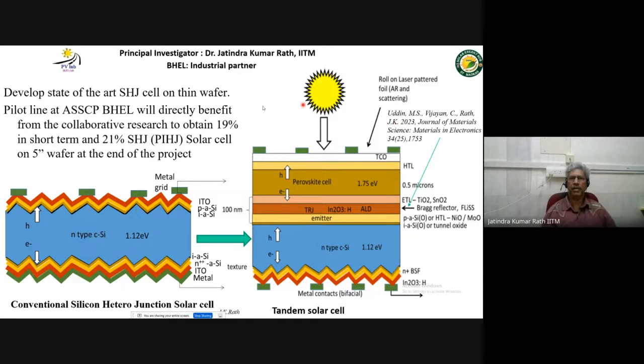So at IIT we have a PhD project to make what is called a heterojunction solar cell. The heterojunction solar cell means crystalline silicon with thin film amorphous silicon as passivating contacts and emitters. So in the PN junction, the P layer is amorphous, whereas the N layer, this absorber layer, is crystalline. So it's a combination of amorphous and crystalline. The PN junction is created between the crystalline absorber and the amorphous emitter, and there is a back surface field to make sure there is no loss inside. And it can be bifacial or monofacial.